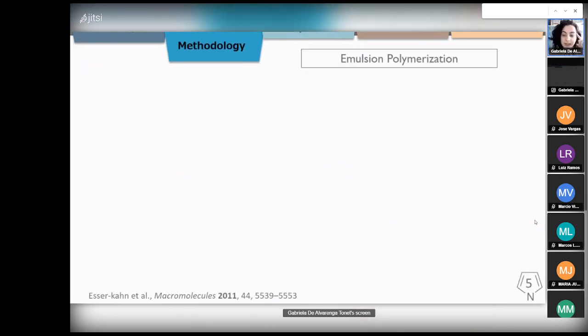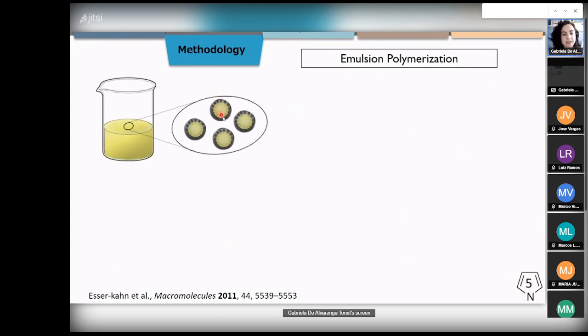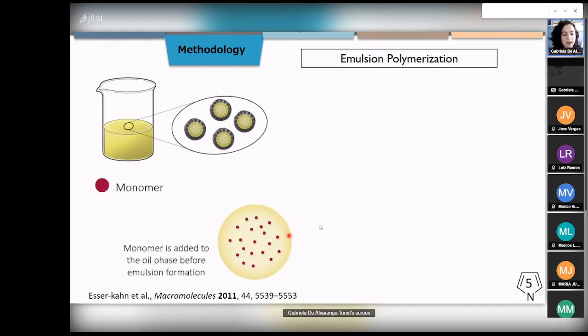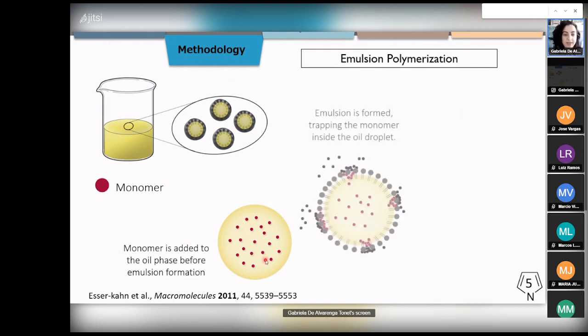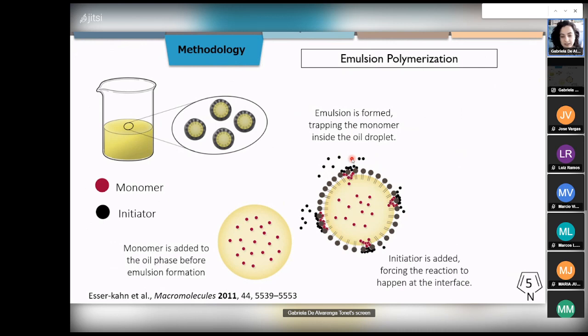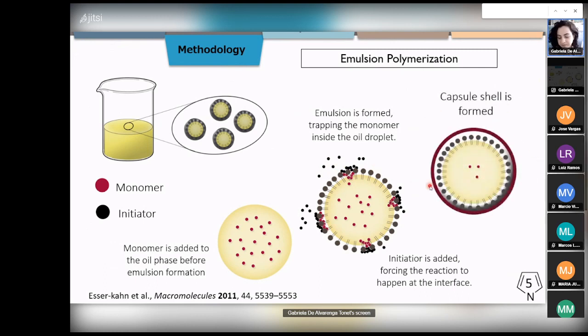So the methodology to make these nanocapsules was emulsion polymerization. Since we are working with the oil, we use this linseed oil to form an emulsion, and we trap the monomer, the pyrrole, inside the oil phase before emulsion formation. Then we add the surfactant, the SDBS, and as a following step, we add the oxidizer or the initiator that will promote the polymerization of this monomer, which is trapped inside the oil core. And then this will force the polymerization to happen at the oil-water interface, forming the capsule shell.